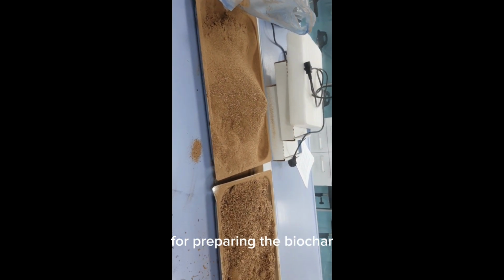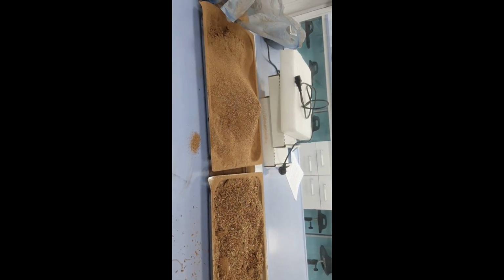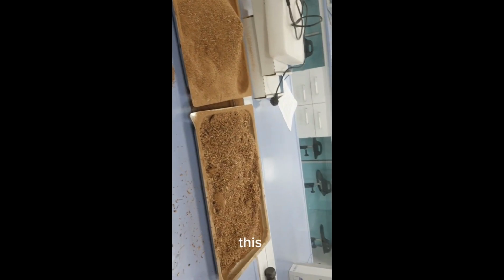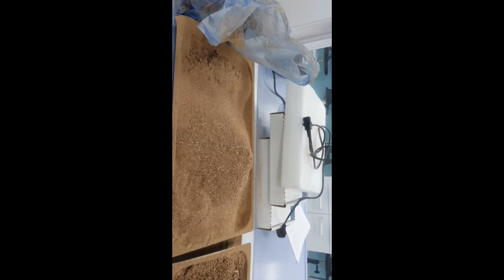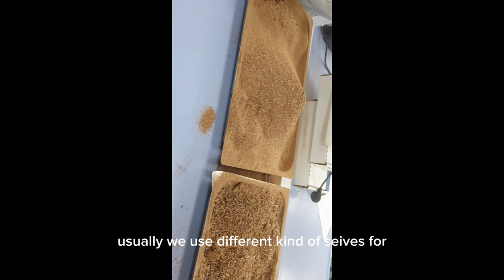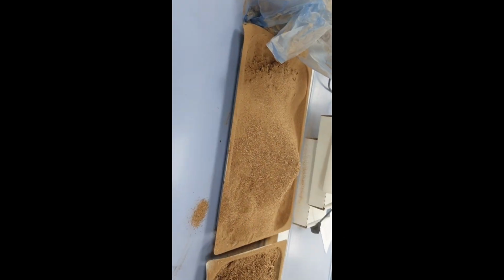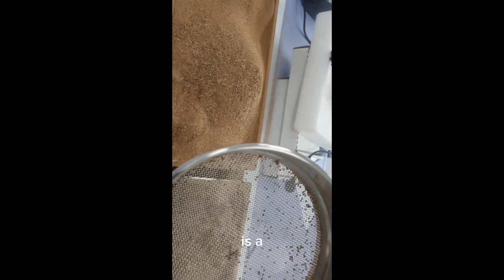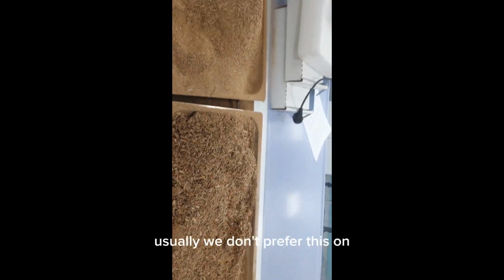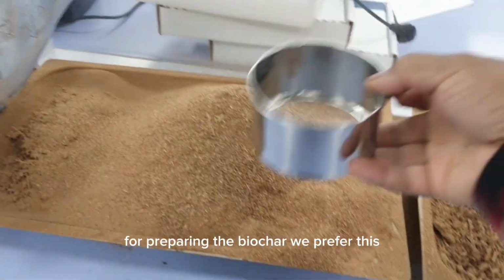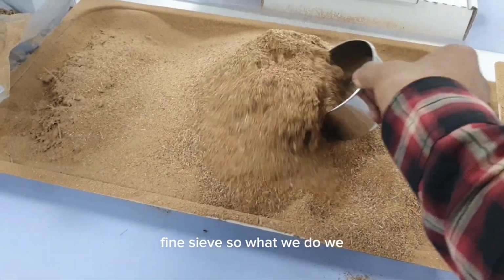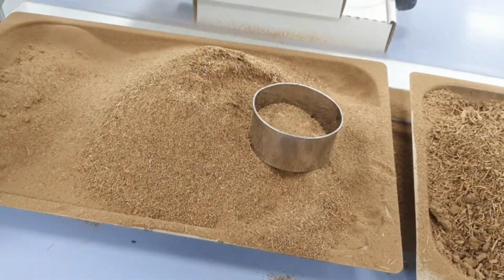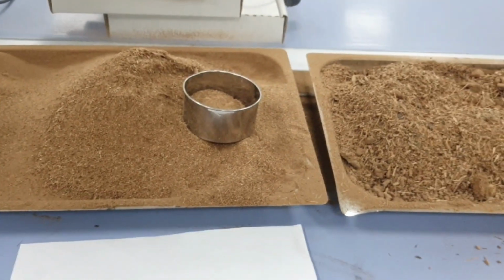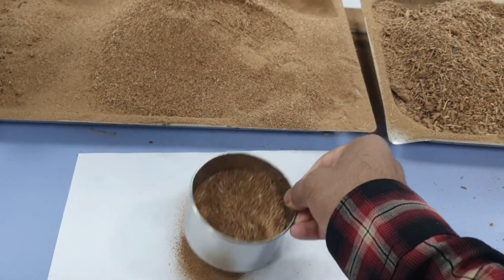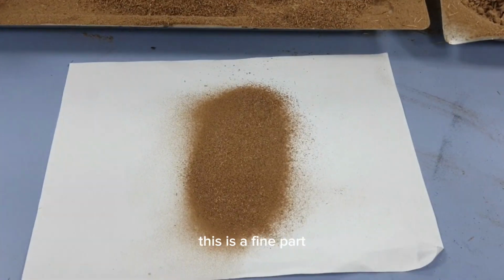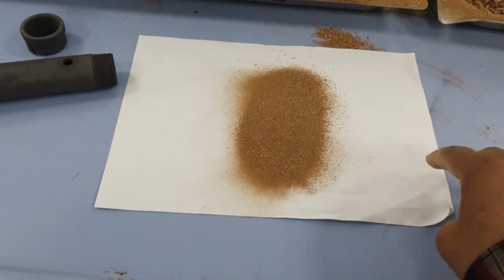So for preparing the biochar, as you can see here, we have dried date palm leaves. This one is shredded, and this one is crushed. Usually, we use different kinds of sieves for taking the fine particles. This sieve is bigger in size, and usually we don't prefer this one. For preparing the biochar, we prefer this fine sieve. So we sieve it and then load it in the stainless steel tubes. This is the fine material that we get after sieving.